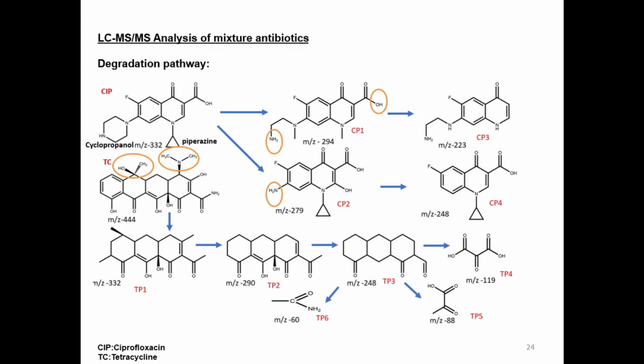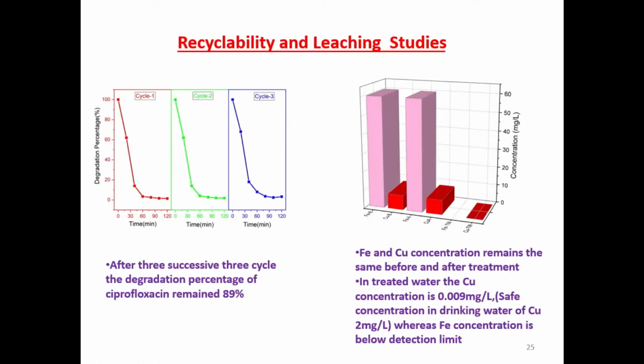Depending on the steps or various intermediates present, we can propose two mechanisms. In one case, you have removal of the amine, this cyclopropanol group, leading to a lower m/z ratio, where the CP1 intermediate is shown, and then removal of the hydroxyl group, which leads to CP3. There can also be removal of the cyclopropanol itself with this intact, which will again lead to a lower m/z ratio. Similarly, in the case of tetracycline, you have a large number of double bonds with higher electron density, and so it directly acts on this higher electron density and leads to a lower m/z ratio. We are still not sure whether these are toxic. We'll see whether it's toxic or not.